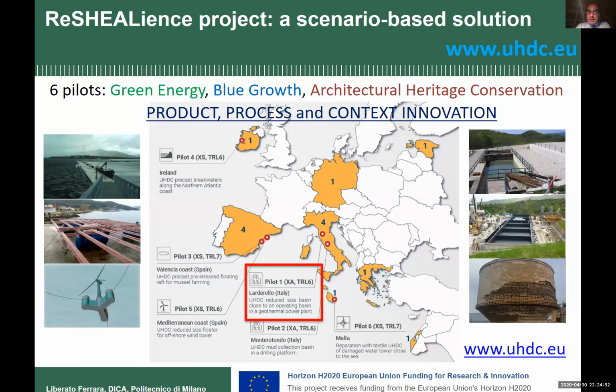So these are different structures in different exposure conditions, because we go from acid attack to chloride attack at different temperatures, since the Mediterranean is different from the North Sea with its wave motion. We also have airborne chloride salts, like in the case of the existing structures in Malta. We used these 6 pilots, designed because they relate to 3 specific cutting-edge sectors of our economy: green energy, blue growth, and architectural heritage conservation.